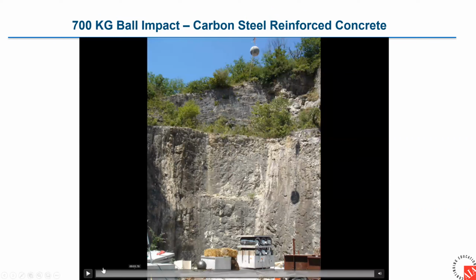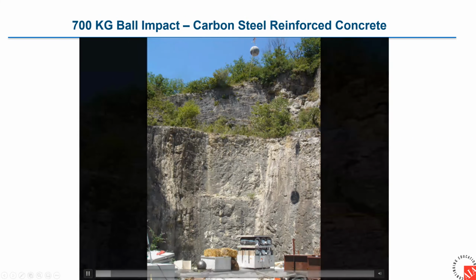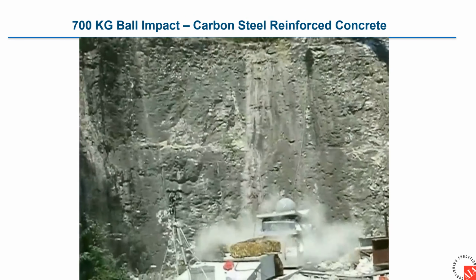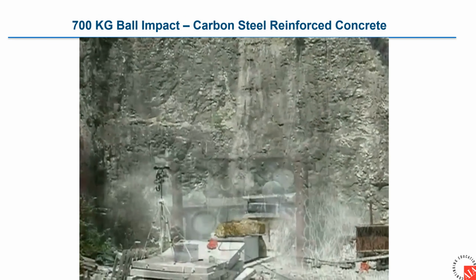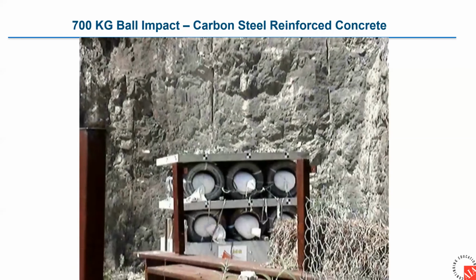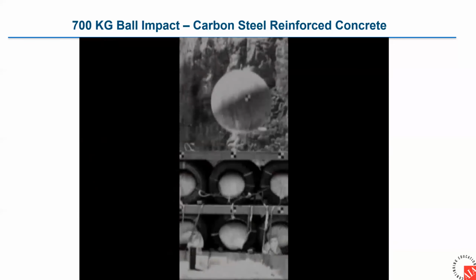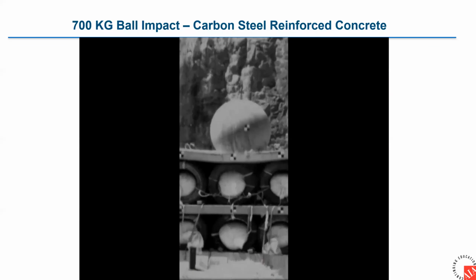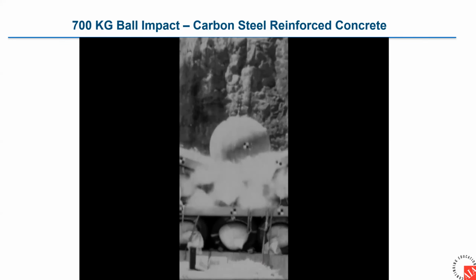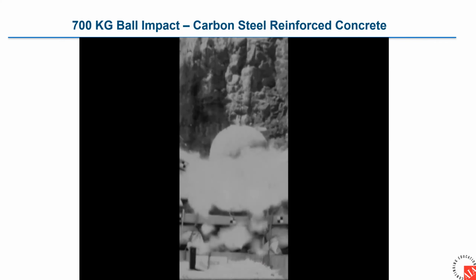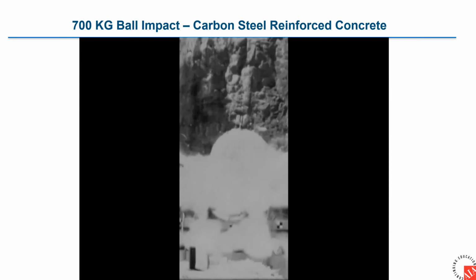And this will give you some idea. This is carbon steel reinforced concrete. The French dropped a 700 kilogram ball on top of it. This gives you the best view. As you can clearly see, not only did the concrete crumble, but the carbon steel failed. This was avalanche wall work, but it's equally applicable to security barriers.